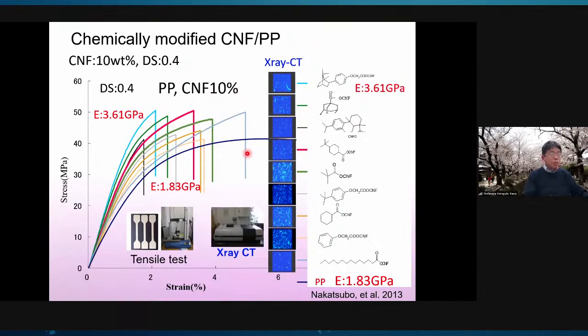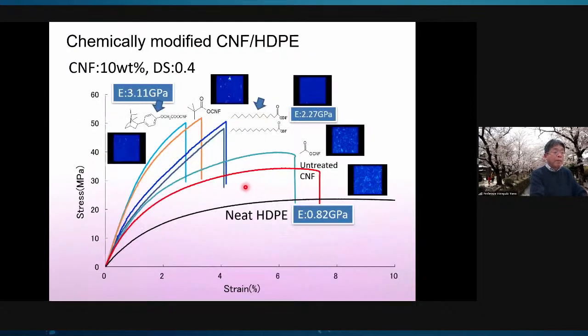This is a part of the results of mechanical properties for PP with 10 weight % CNF added. We clarify the relationship between reinforcing efficiency, the chemical structure incorporated, and the dispersibility of CNFs at DS of 0.4. This is a result for polypropylene, and this is a result for high density polyethylene. You can see that the longer chain improves dispersibility of CNF in polyethylene and increases mechanical reinforcing efficiency. However, it was found that incorporation of a rigid structure gave higher reinforcing efficiency than a long alkyl chain.